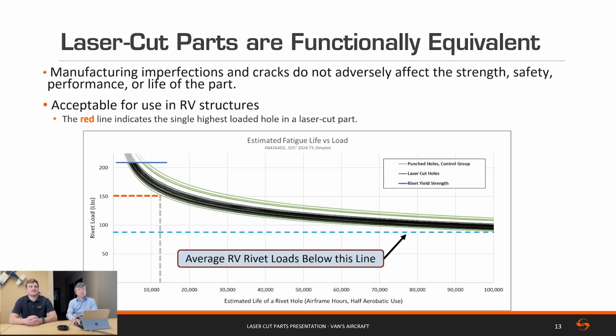The highest load we have in any RV wing is 150 pounds at a 3/32 fastener. Realistic use, if we were to change the scale effectively for an average RV use case, would expect 10 times higher life. So if we look here at our 150-pound highest load in the wing, project it down to that 13,000 airframe hours under that very conservative use case, we can then multiply up to roughly 120,000 hours for what we would expect is still a conservative RV type of flying for that single hole. Again, that's the onset of cracking from the highest load of that peak load hole.